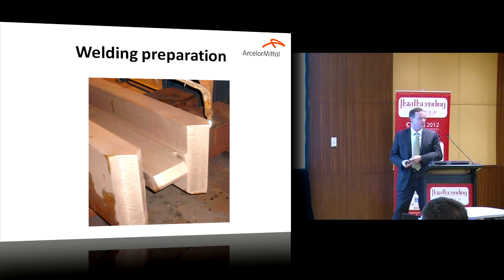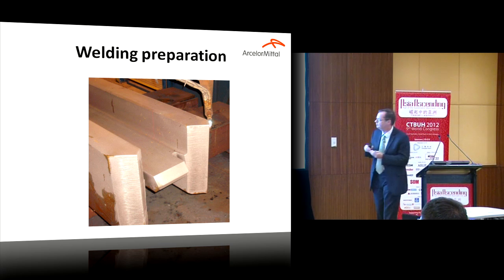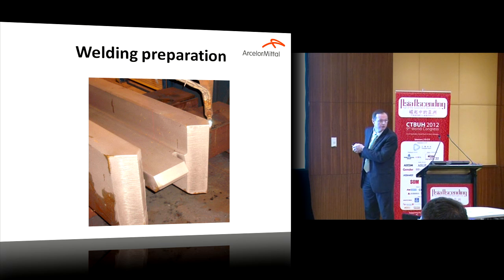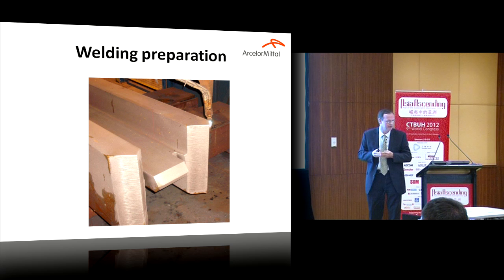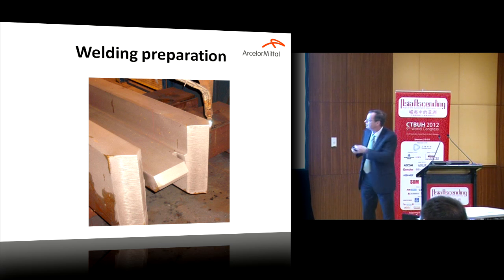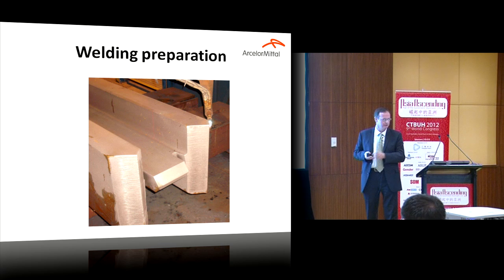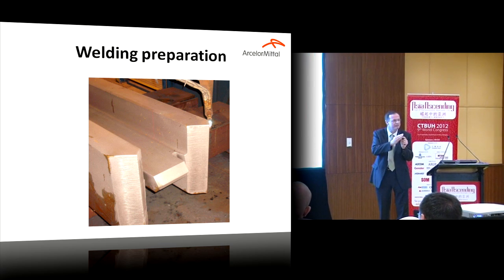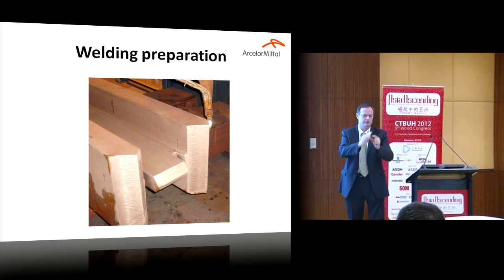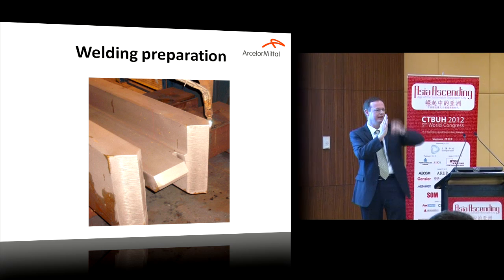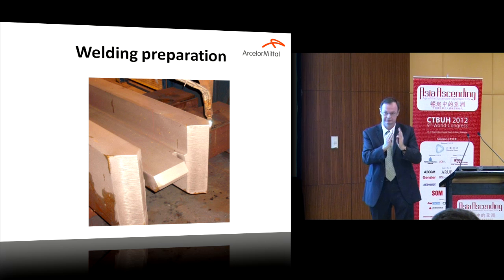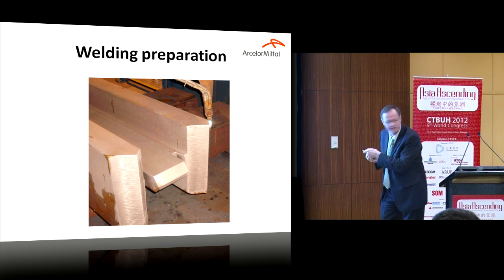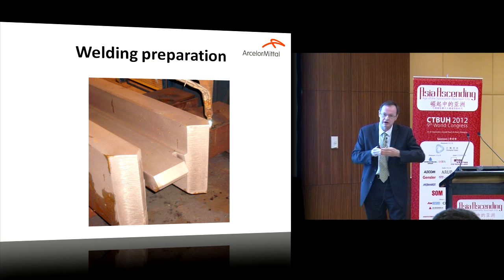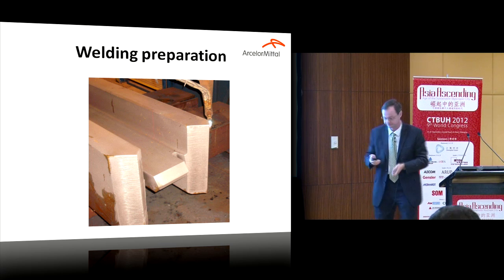This is what Northridge taught us. When you have to splice two jumbos, you must do what we call a rat hole, an access web, not to put weld in this region because you have a high level of stresses. When they weld the caissons, first they do not do a bevel. The code says above 10 millimeters, you need a bevel if you want a full penetration weld. Here they are welding just a small gap, filling a small gap between two heavy plates. So you need to do this type of hole to limit the residual stresses once the weld shrinks.